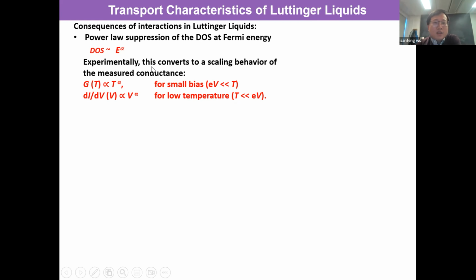Experimentally, this will convert to the transport behavior as follows. If the density of states is proportional to E to the alpha, where alpha is the exponent, then conductance should be proportional to T to the alpha, because T provides the energy. Or you can also measure as a function of the voltage bias that you applied. In this case, we should measure differential conductance, which should also reveal the same exponents that reflect the interaction and the suppression of the density of states at the Fermi energy.